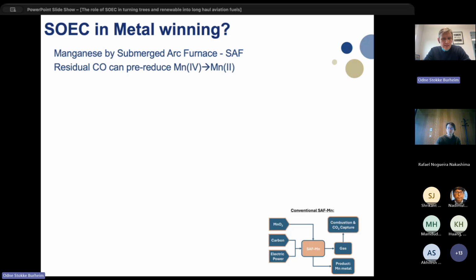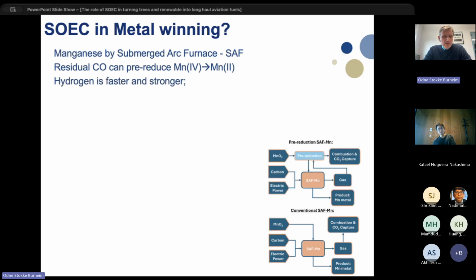So this is an industry that's kind of keen on improving. So what they did next was that they started pre-treating the manganese 4 with carbon monoxide as to get manganese 2, so MnO, going into the submerged arc furnace. It turns out that hydrogen does this several times faster. The hydrogen is a much better pre-reducing agent for manganese.